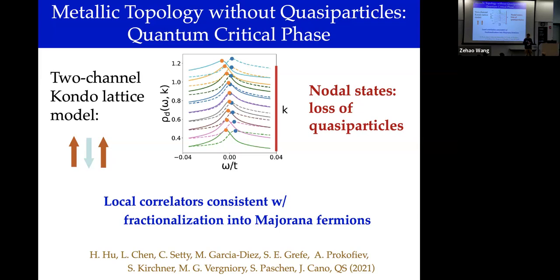So we cannot probe these fractionalized excitations directly. That's one of the outstanding challenges of the correlated electron field. But we can measure the physical object correlation functions. And so the square root omega of self-energy, which is like a T matrix that the conduction electron experiences, captures this consequence of Majorana fermions that's consistent with that.